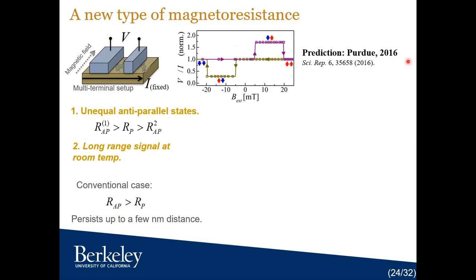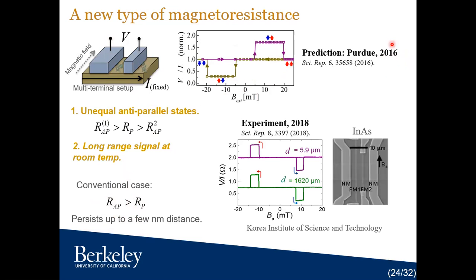We predicted this around 2016, and later it was demonstrated on indium arsenide by our collaborators at the Korea Institute of Science and Technology. They demonstrated these unequal anti-parallel states at room temperature, and they shifted the contact from 5.9 micrometers up to 1.62 millimeters, which is a very long distance, and the signal did not degrade at all, which was one of the major conclusions of the theoretical model. So this physics is very interesting.